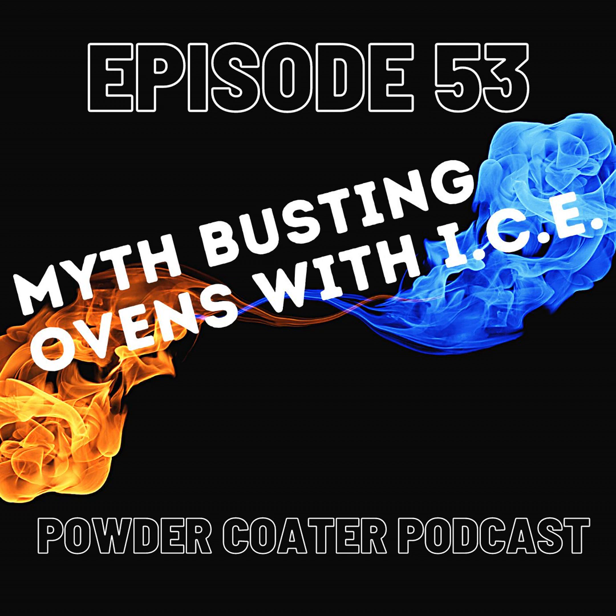And that really brings a good point too. A lot of people will run into issues where they use a high velocity air seal because they're worried about heat getting out of the oven and into the building. Well, when they're hitting that freshly sprayed powder with that high velocity of air, you are discharging a good amount of that. And eventually you have a coating throughout your oven of this powder. And then you go in there, you try and clean it. Now you're dislodging it, and that creates some issues. But in general, for most applications, it's not really a problem. Now, qualifying that by most of my customers aren't looking for a Class A finish or something like that.